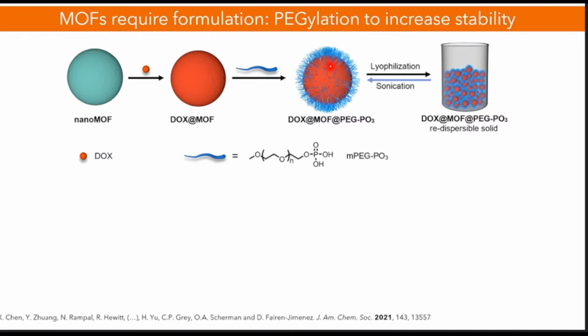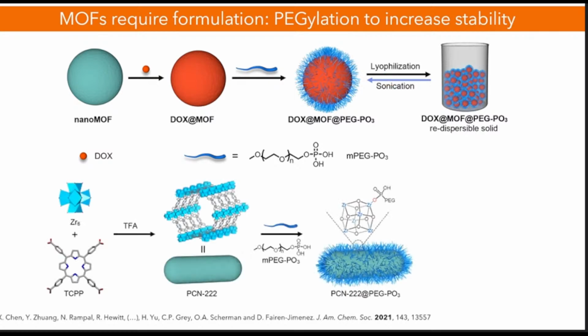Not only can we protect the material, we can also include some lyophilization. So we can basically dry these materials, we can get some solid samples that we can really redisperse into solution. And this helped us quite a lot in the translation of these materials to the clinic. This is basically the materials we were working with. One example is PCN-222: this is the metal cluster, the organic molecule, the one-dimensional channels that we have, and the pegylation.